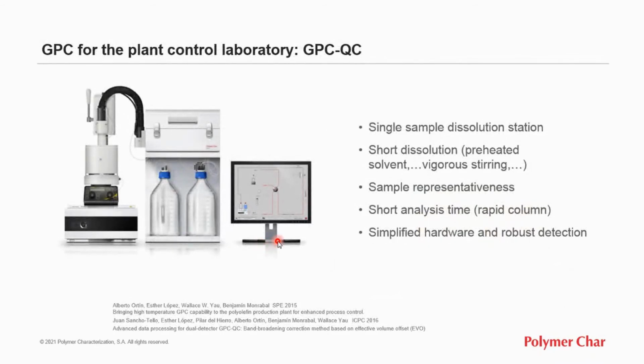So with those principles in mind, we developed GPC QC as a simplified GPC instrument optimized for the manufacturing laboratory. Given the application for GPC QC is following the process changes in manufacturing, it demands the analysis of a single sample of material which is produced at a particular time. Then some time later, another sample from the process is coming, and so on. That means that there is no need for a sophisticated autosampler with many vials, but a single sample dissolution station, which is optimized to shorten the dissolution time by filling automatically with preheated solvent and applying vigorous stirring.